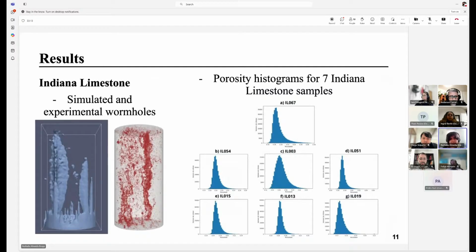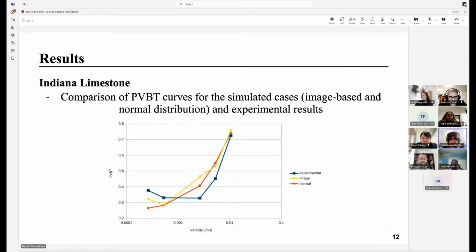And here we see the PVBT curves, the acidizing efficiency curves dependent on the injection velocity. The image-based case, here in yellow, and the normal distribution case end up very close to each other, and they also have only small differences from the experimental curves. So for the Indiana limestone system, using an image-based porosity field or a normal distribution ends up being quite equivalent.